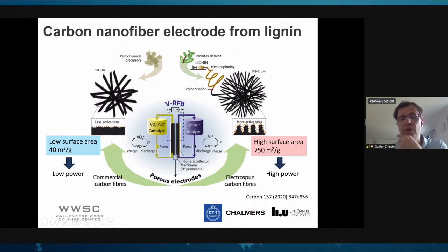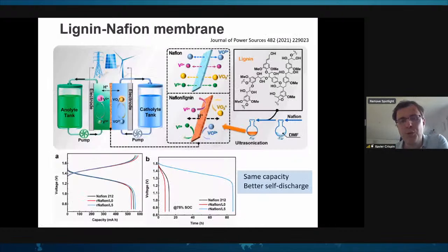So the next thing that lignin has been used for is to combine it with Nafion. Nafion is a membrane that has been used because of its chemical stability in these vanadium redox flow batteries, in a very strong acid, basically. The problem of Nafion is that it is not very good for this kind of ion, because the ions are crossing the Nafion quite a lot, and this is a problem for the battery.